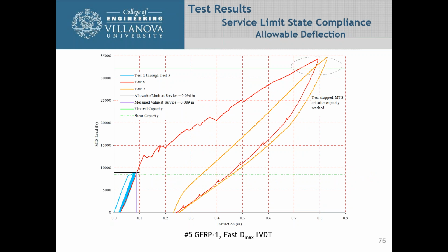And the next thing we want to look at is the allowable deflections. We show the same type of curve. Now the difference here is the allowable limit is down here, which is the 0.096, and this is for number 5 GFRP bar, and this was on one of the east side LVDTs, and this is the maximum deflection point, and you can see our maximum measured that we ended up with was 0.089. So again, we're in compliance.